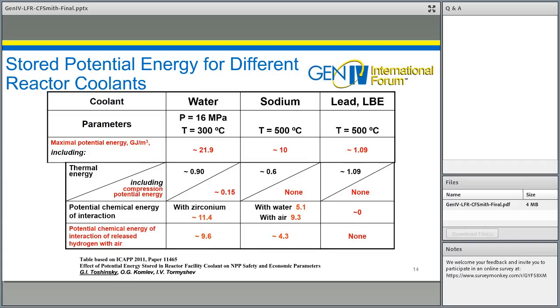The bottom line is that water as a coolant presents 21.9 gigajoules per cubic meter of stored energy. Sodium, less than half of that figure, at 10 gigajoules per cubic meter, and lead a further reduction of about an order of magnitude down to 1.09 gigajoules per cubic meter of stored energy. The very low comparative amount of stored energy in lead-cooled fast reactor coolants is another indication of their enhanced safety potential based on intrinsic properties of the coolant.